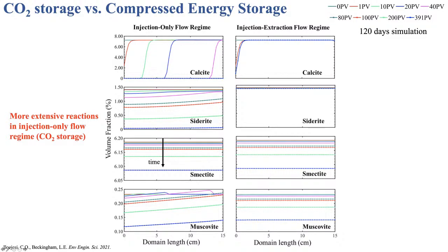On the right here are the results for the injection extraction flow regime corresponding to energy storage. You can see we have some calcite dissolution closest to the boundary with the CO2, but then really no further dissolution further into the formation. We have really minimal siderite dissolution. We do have some smectite and muscovite dissolution across the domain, but overall the reactions are much more extensive in a CO2 sequestration system, where you're getting limitations in the extent of reactions here from flow cycling.